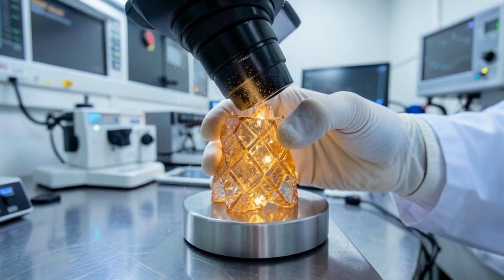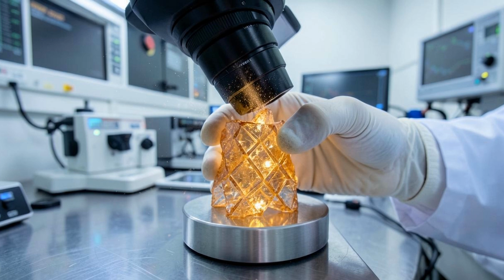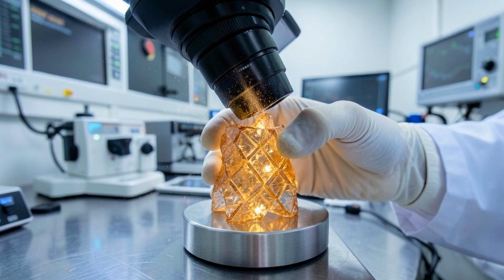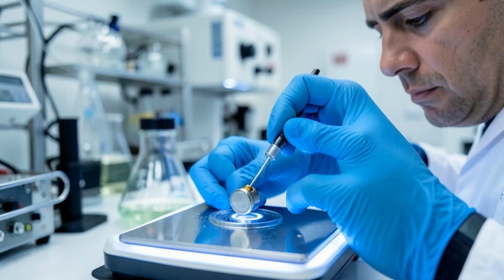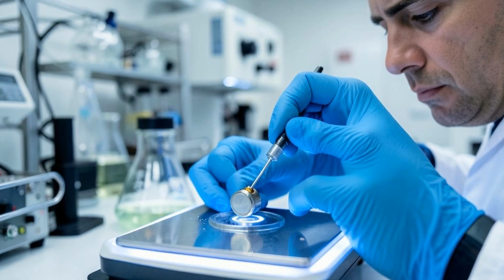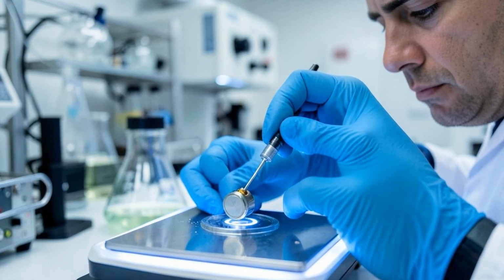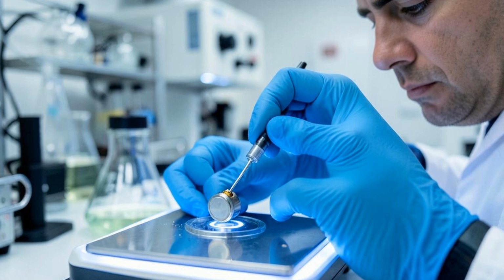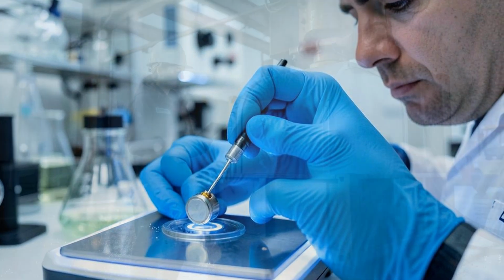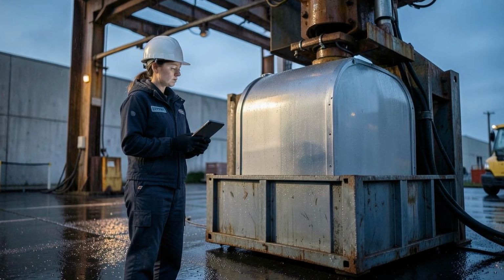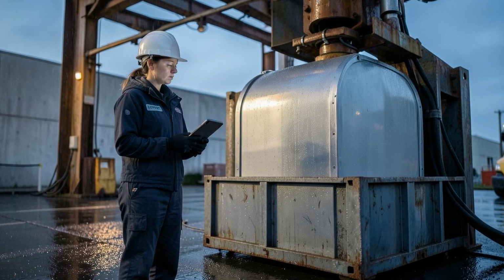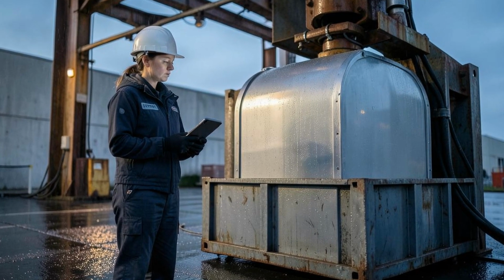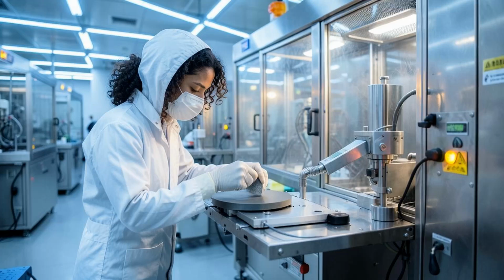This is not just mixing two metals together, it is an architectural change to how ions move through the material. The breakthrough lies in how this magnesium-tin combination regulates ion transport during charging and discharging cycles. By doing so, it suppresses the formation of dendrites, tiny spikes that can short-circuit a battery, and stabilizes the solid electrolyte interface layer that protects the anode surface.